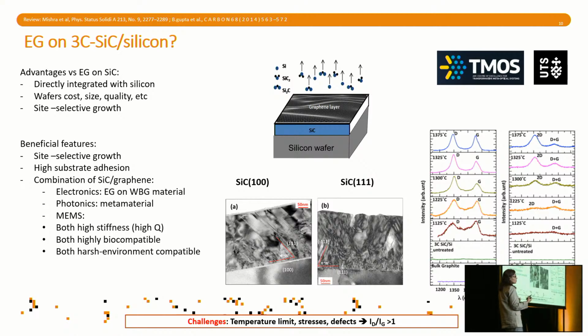But if you're able to do that, there's a lot of gain to be had. Why is this? Because you can have site-selective growth, and I'll show you in a minute, because you're still relying on the solid source given by the silicon carbide. You can have potentially higher adhesion, and I'll talk about that. And then particularly, the combination of silicon carbide and graphene is really very beneficial. I will show you some examples for the metamaterials, and also for the MEMS and the biosensing.